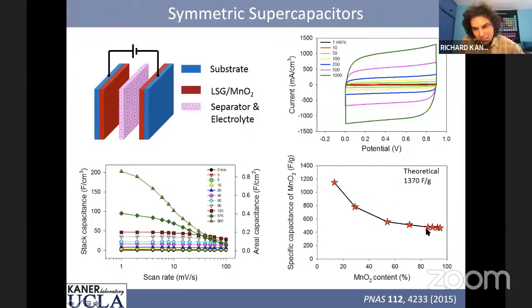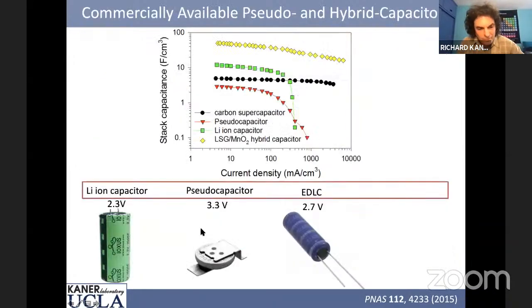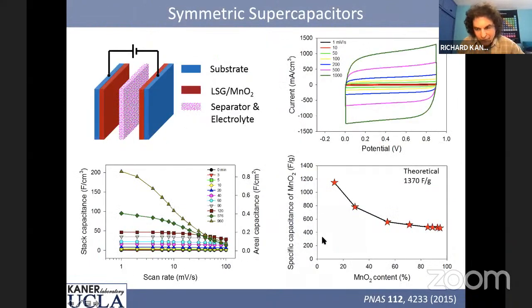On a practical level, you really want to go the other way. You want to use very little graphene and a lot of manganese dioxide, just because manganese dioxide is so cheap. And if we go to about 5% graphene and 95% manganese dioxide, you can see we can extract on the order of 500 farads per gram. And so this stuff works quite well. And what this says is that the way you should use graphene for energy storage is graphene should just be the scaffold, and you can stuff all sorts of battery materials into it. And so we're excited about that possibility.